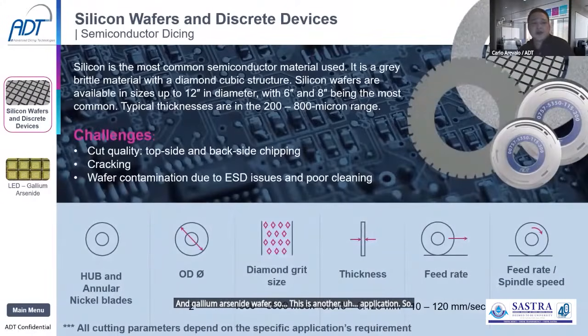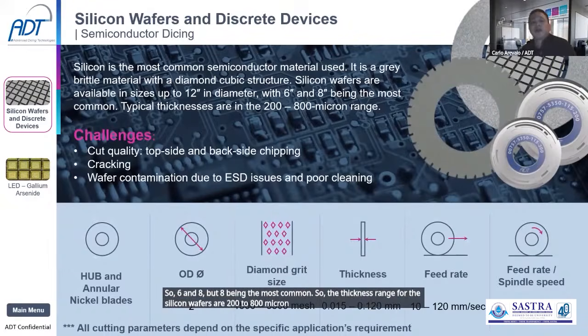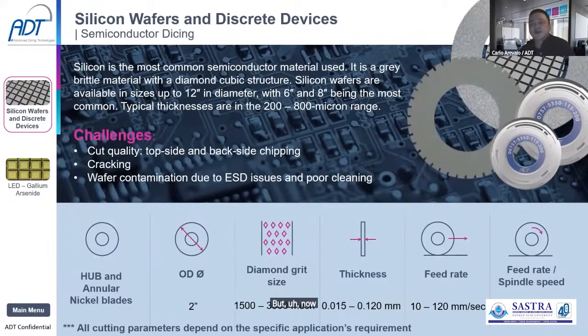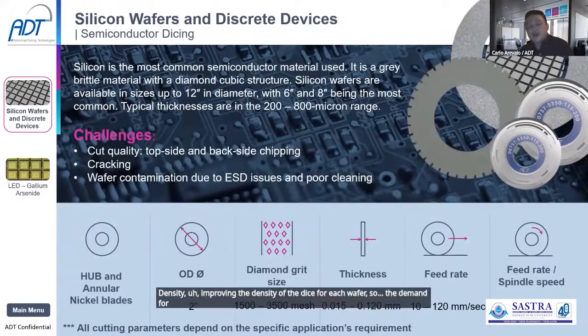So silicon is the most common material. It is brittle, and the wafers range from 12 inches diameter to 6 and 8, but 8 being the most common. The thickness range for the silicon wafers is 200 to 800 micron. But now the industry is of course improving the density of the dies for each wafer. So the demand for the streets to be very narrow is very common.